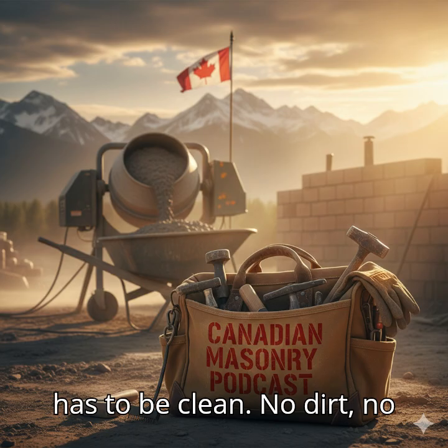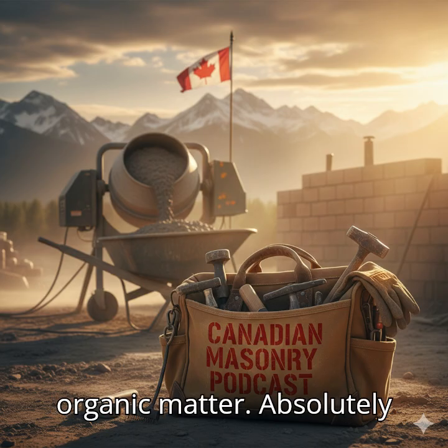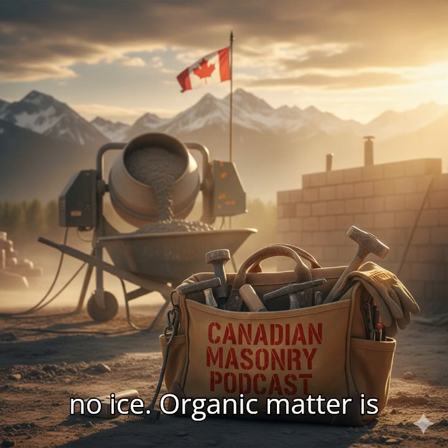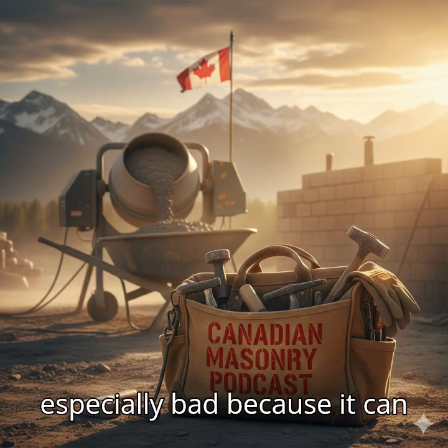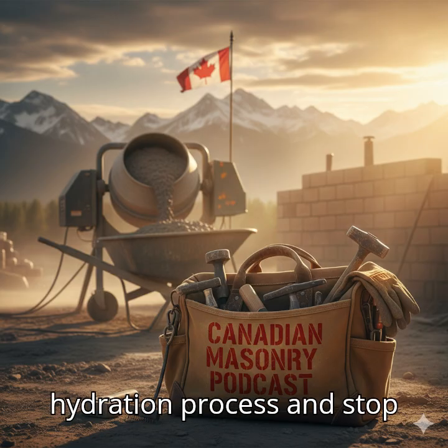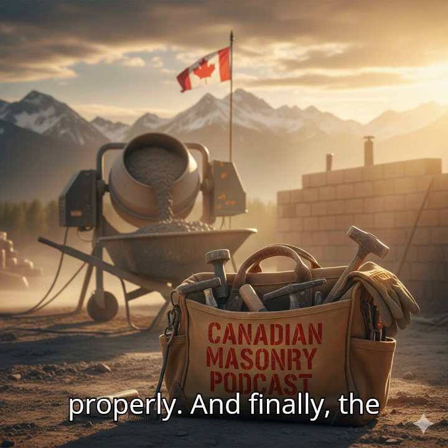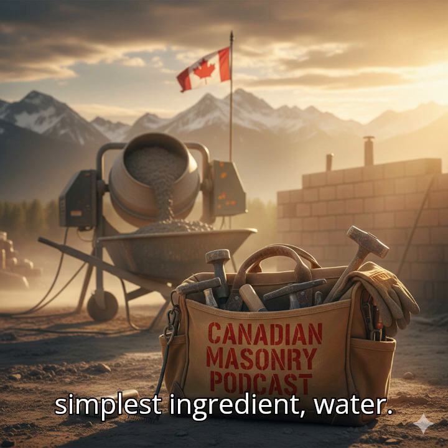and it has to be clean. No dirt, no organic matter. Absolutely nothing. No oils, no salts, no ice. Organic matter is especially bad because it can completely mess with the hydration process and stop the mortar from setting properly. And finally, the simplest ingredient, water.